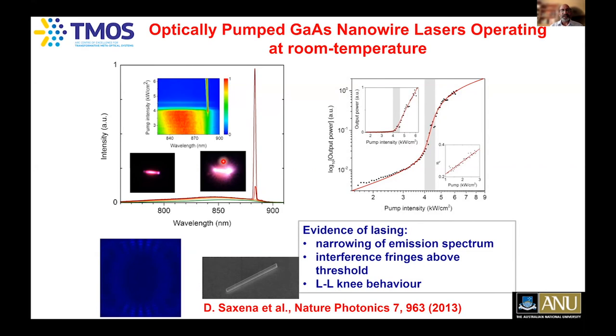In fact, Dhruv Saxena simulated what type of patterns you can see. You can see beautiful interference fringes because two coherent dipoles are emitted from both ends of the nanowire, and he compared the simulations and they match very well. We published this work close to a decade ago in Nature Photonics, by Dhruv Saxena, and he has since gone off and is now working at Imperial College.